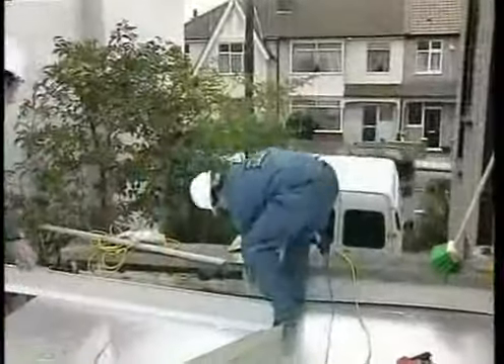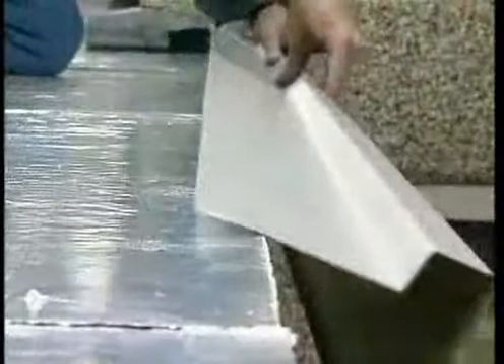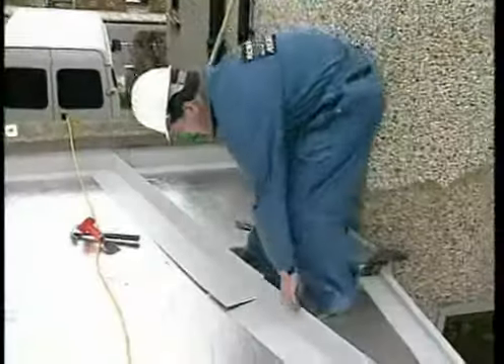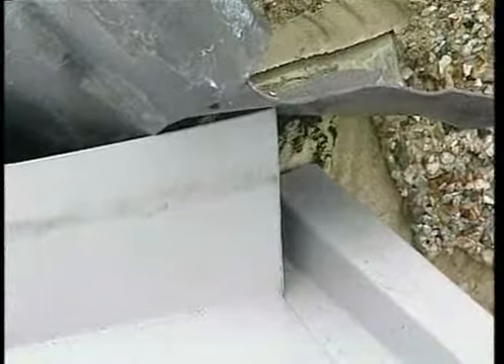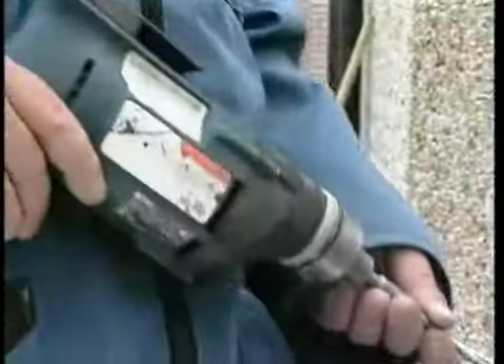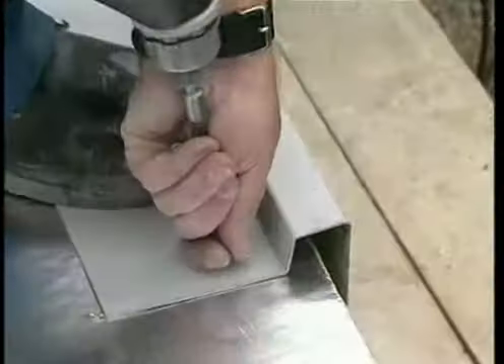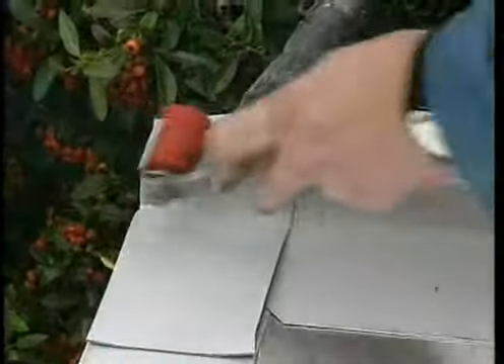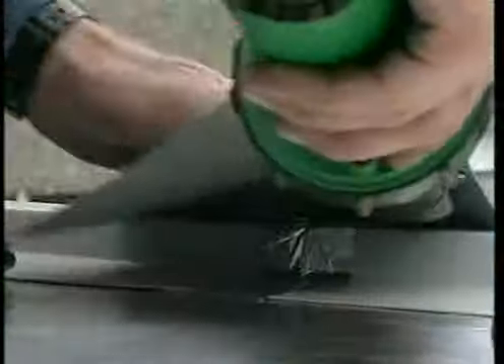Once the insulation has been laid, the Alkor metal edge details are fixed. Alkor metal consists of galvanized steel sheet, laminated to a layer of membrane. The metal sheets are cut and bent to the required shape prior to being brought to the site by the approved contractor. Alkor metal sections are used for the upstands, rain checks and drip edges located around the perimeter of the roof and are fixed into position using self-tapping screws at 150 mm centres. The same process is used for parapets, plant bases and roof light curbs.